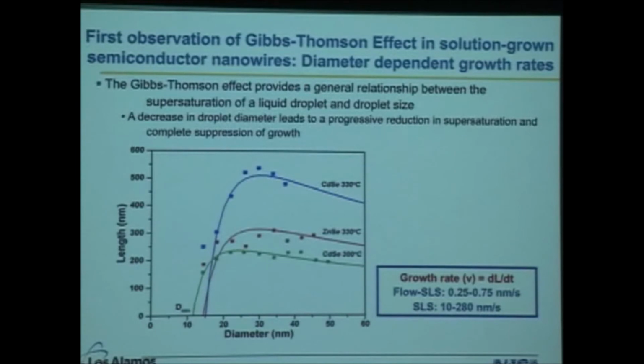And then if we do, like my former postdoc Raiwan Lao Sharanshuk did, a very, very careful analysis of the relationship between length and diameter and growth rates, we found a clear indication of the Gibbs-Thomson effect for the first time in the solution-grown system. So this is commonly observed in VLS-grown nanowires, and this is the first observation in the SLS world of diameter-dependent growth rates. And so what you find is that for very much smaller diameters, your growth rates are suppressed due to this effect.